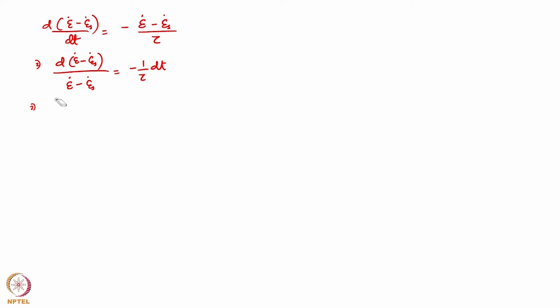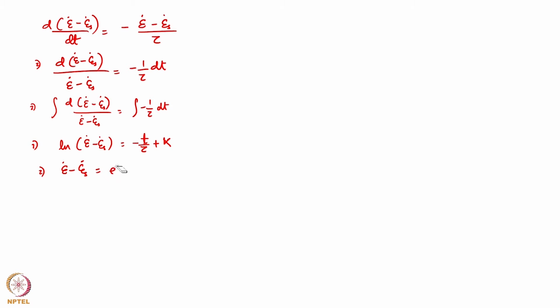Now, if we carry out integration of this, that will lead us to ln of (epsilon dot minus epsilon s dot) equal to minus t by tau plus some constant k. So, this implies epsilon dot minus epsilon s dot is equal to e to the power minus t over tau into e to the power k. Tau, as I mentioned, is the relaxation time for rearrangement of dislocations, and 1 over tau can also be written as r, which is the rate of exhaustion of transient creep.